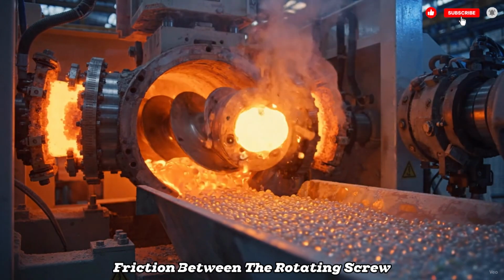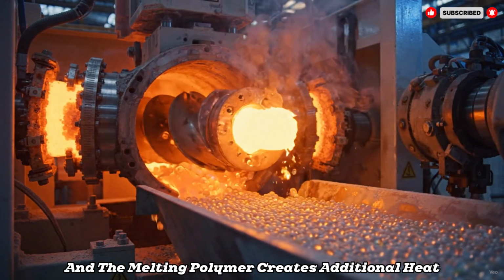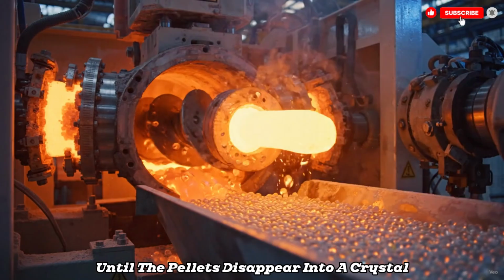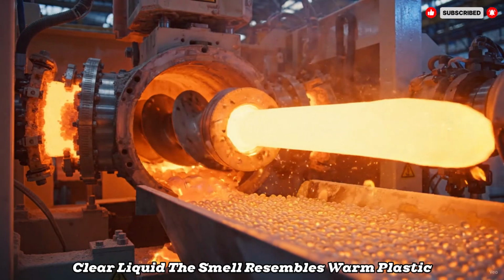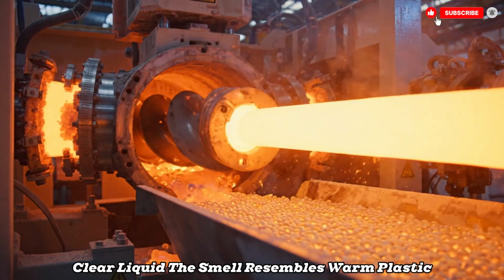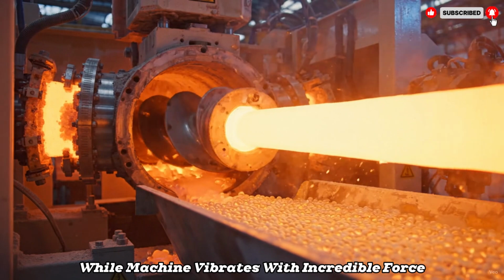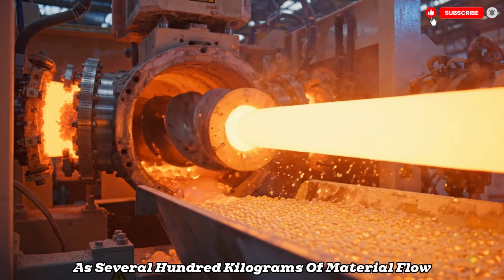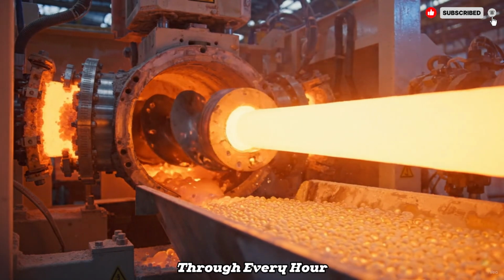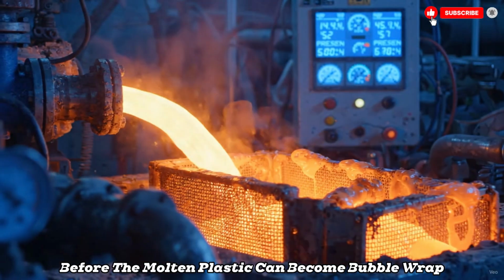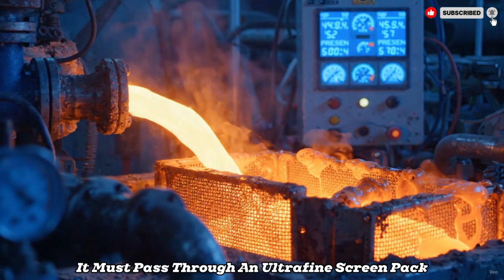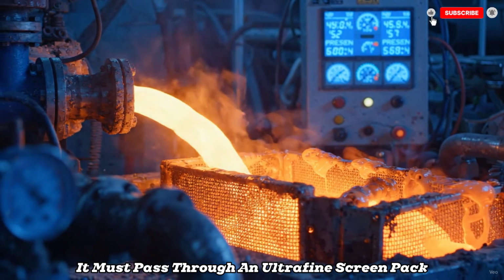Friction between the rotating screw and the melting polymer creates additional heat until the pellets disappear into a crystal-clear liquid. The smell resembles warm plastic, while the machine vibrates with incredible force as several hundred kilograms of material flow through every hour. Before the molten plastic can become bubble wrap, it must pass through an ultrafine screen pack that filters